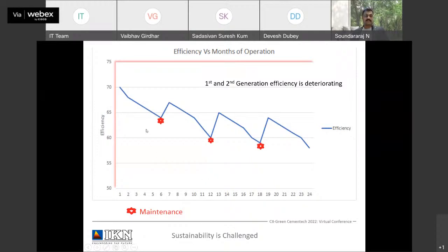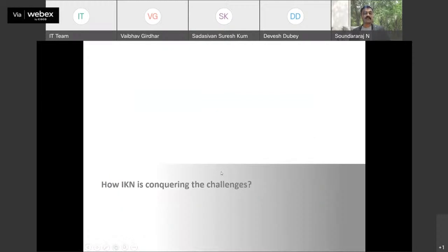You can see that cooler efficiency is dropping down over the period of time. Why? Increase in the gap, mixing of the clinker bed, wear and tear, and heat distortions. The original gaps could not be attained despite many efforts by the mechanical team. Thanks to the mechanical team, at least they could try to improve up to some extent during every shutdown, but it is not sustaining. Again, it is deteriorating. So it could not reach the original number at any cost despite many attempts. Then the sustainability of the results is challenged.